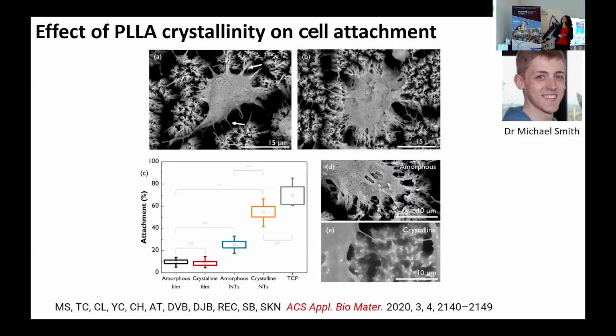And Mike, who was a PhD in the group, he then started these first experiments where we started to put cells onto these nanowire arrays just to see what they do. And the first thing we noticed is they loved these nanowire arrays because these are basically rough nanostructured surfaces. So you can see these are human fibroblasts, dermal fibroblasts, so skin cells. They let out these cellular projections. They're grabbing, they're pulling, which is exactly what we want because this means that they're shearing these nanowires and we can detect this. And he did this for amorphous as well as crystalline nanowires, and we saw a difference in the way the cells behave.